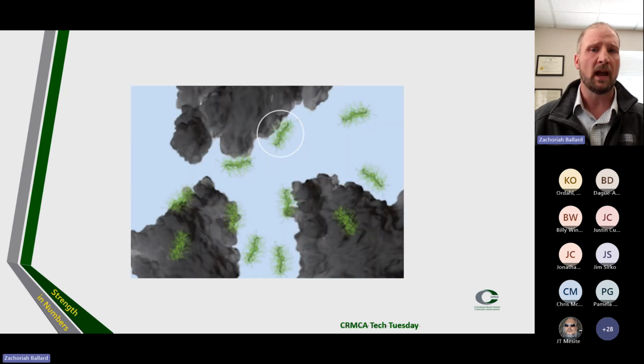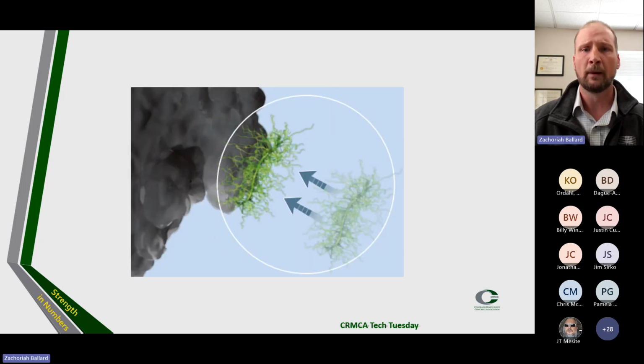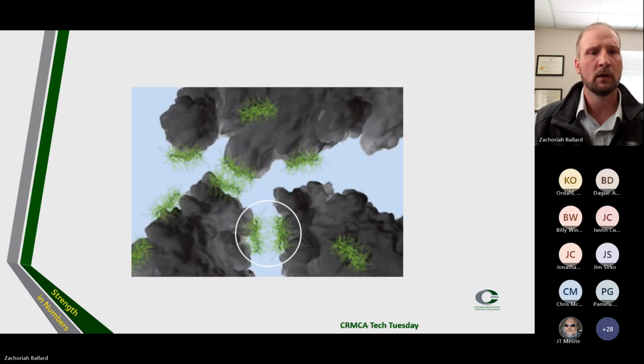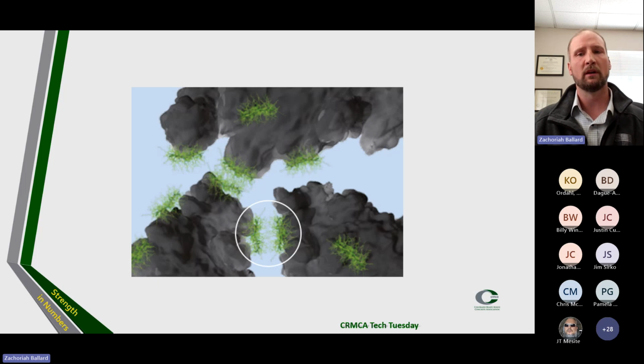So we get the adsorption of the polymer, the backbone, onto our cement grain. This is a detail of that adsorption of the polymer onto the cement grain, and the improved workability due to steric hindrance. Steric hindrance is a slowing of a chemical reaction due to what's called steric bulk.